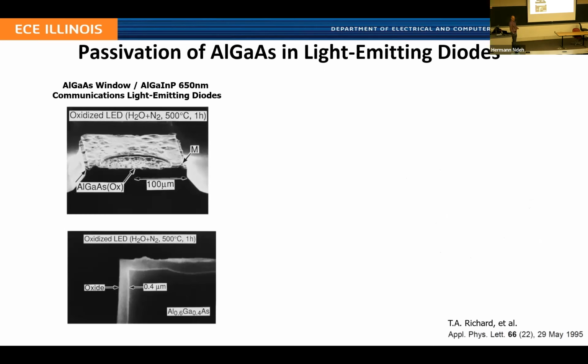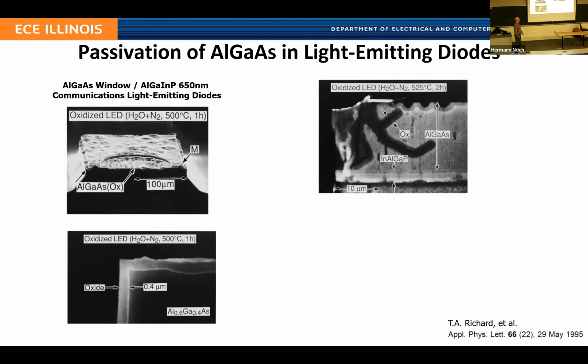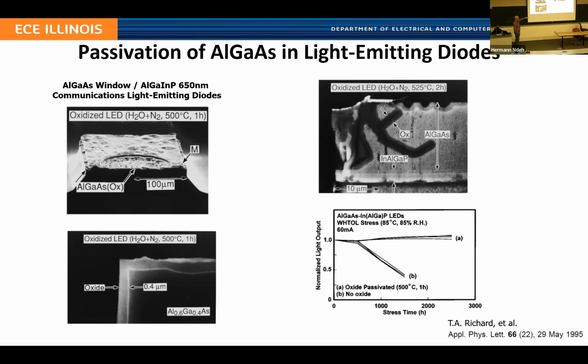In addition, the oxide being very dense was able to serve as a hermetic seal. We took red emitting communications LEDs with an AlGaAs window and oxidized them post fabrication, and with that we were able to form a hermetic seal around the window, and not just around the window, but around any imperfections. These are cracks that originated at the side of the device from sawing, for example, and these were also sealed by the oxide. That enabled the devices to withstand wet hot testing. 85 degrees C, 85% relative humidity was a killer for these devices. It was a real problem. With the post-oxidation treatment, they were able to pass the 85/85 reliability test. These are the LEDs that people use for plastic optical fiber communications.